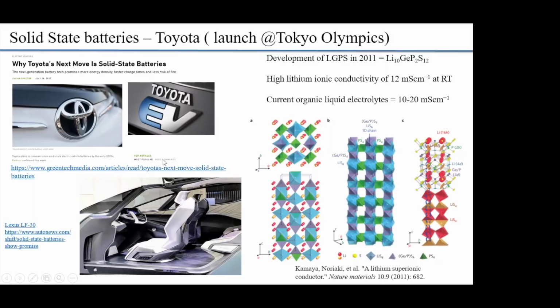So this goes back to 2011. In 2011, they developed this material called LGPS, lithium germanium phosphorus sulfide. At that time, it was pretty remarkable because it had 12 millisiemens per centimeter at room temperature, whereas organic liquid electrolytes have about 10 to 20. Basically, you can look at this material as a huge building with multiple hundreds of rooms, and there are hallways which are open for lithium to move. So lithium can traverse from one end to the other because there's an open pathway, like long one-directional hallways in a building. That is really conducive for lithium transport.